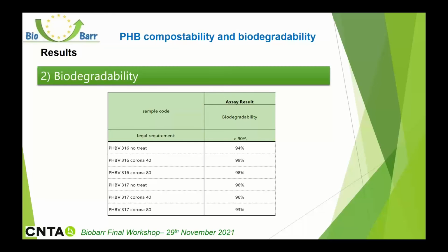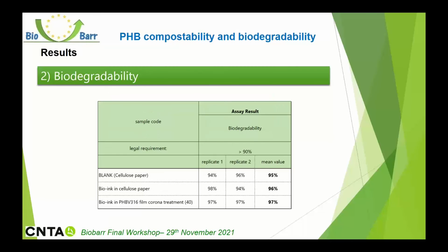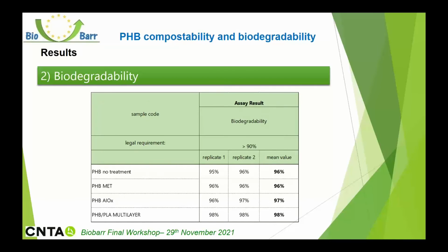Regarding the second essay, biodegradability, as you can see in this table, our first prototypes passed the criteria of biodegradability. The criteria is 90%. Similar result with bioinks. The two test bioinks, because one is the control, fulfill the biodegradability criteria too. And finally, this table shows the result of the biodegradability assay with the 4 final prototypes. As you can see, these polymers also pass the biodegradability requirement.